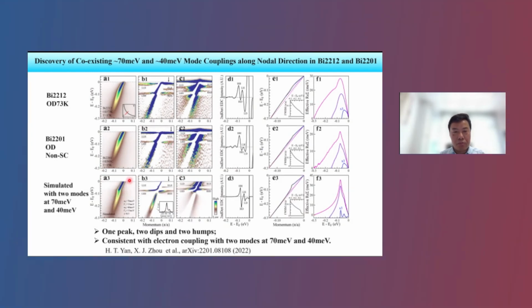You put in a two mode coupling, one at 40 millivolt, one at 70 millivolt. You do a simulation. You can see the simulation is very similar to the observed band here. So this means along the nodal direction, the 70 millivolt and 40 millivolt mode couplings are coexisting. It has both mode couplings along the nodal direction here.